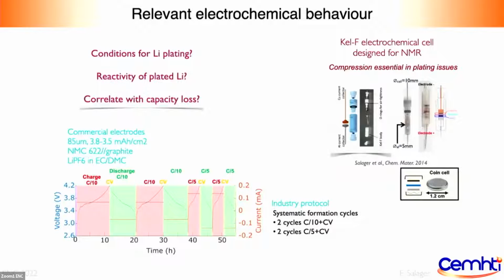And so we've been working on getting relevant electrochemical behavior. That's the most important if we're doing in situ NMR. And to be honest, I think we still have work to do on that subject. So what we did is that we used the cell we devised previously, because for plating, we know that compression is very important. Tests on pouch cells that are not compressed show that you get plating much earlier than what you would get in a real battery.